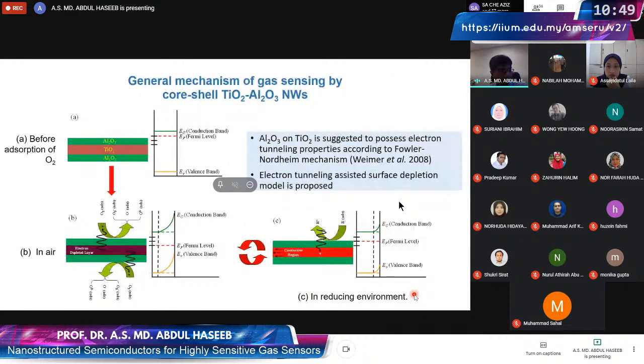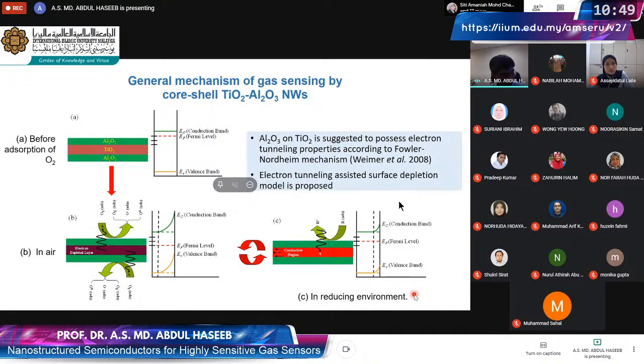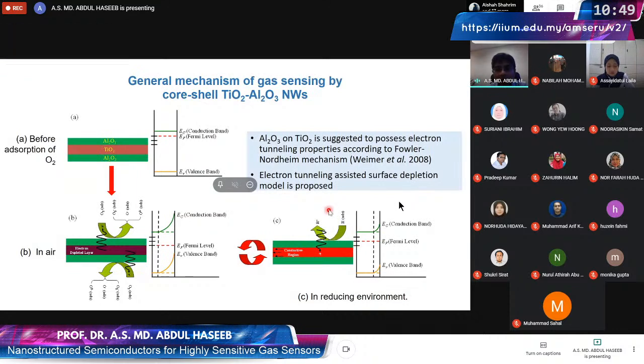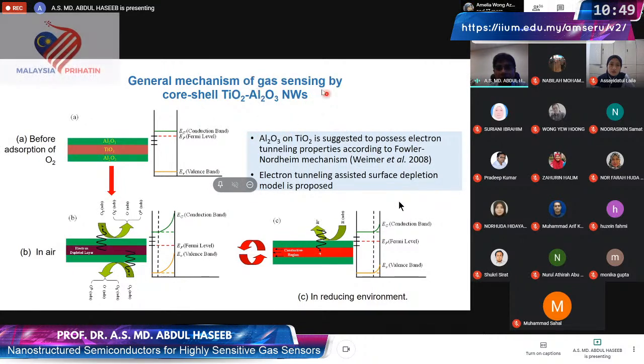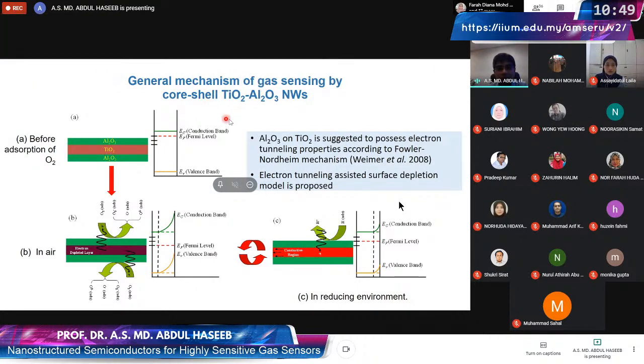And here is the description of the mechanism. I probably will not go into depth because my time is running quite fast, as I can see. So I just want to highlight one particular thing. You probably have in your mind why aluminum oxide, because we know that aluminum oxide has a band gap of more than 8 electron volts. So this is a true insulator. Whereas we need a semiconductor with a band gap of 3 plus electron volts.